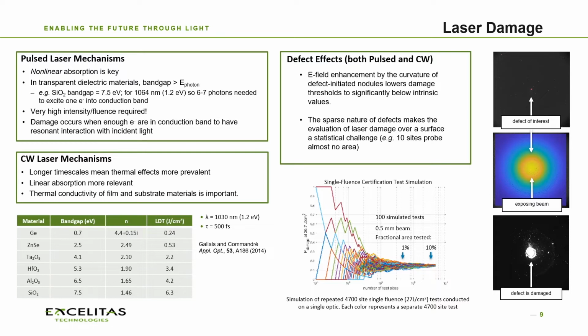Now that can be enhanced by these other things. So if the linear absorption is high, or if the band gap is too low in CW and pulsed applications respectively, what's going to happen is the defect is going to enhance that. It causes a field enhancement effect that's going to induce damage at a lower threshold than would normally be the case if the defect was not present.